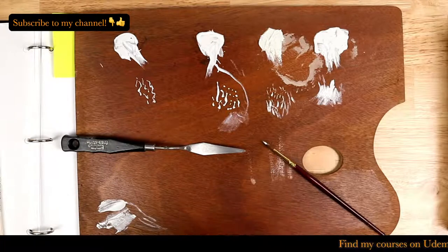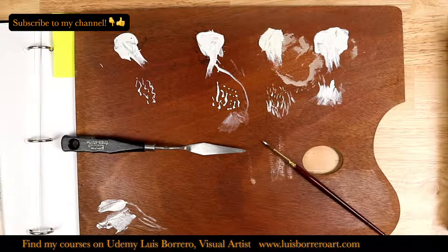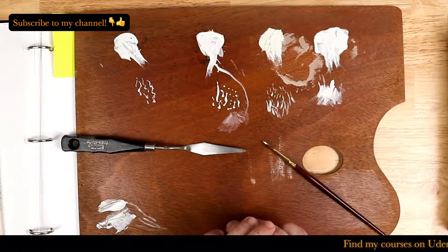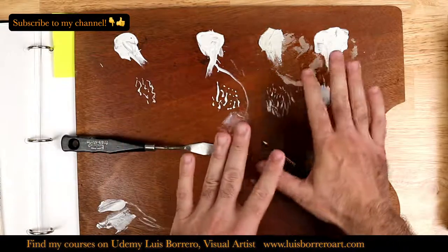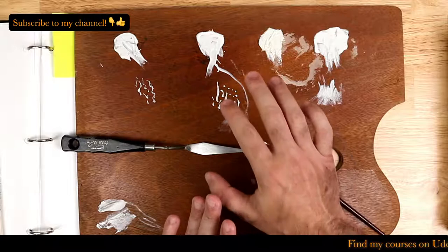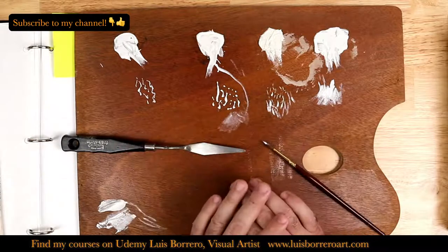Let's see. I have another question from Enzo. Did you have any negative interaction problems with other colors? I have not. I have been making this pigment for 20 years, and I have never had any problems with the lead white interacting or turning black. There's some documentation that says that it turns black. Now, if it's not properly washed, you will have problems. The pigment will not be serviceable. It's going to be a very yellow paint, so it's important to wash it thoroughly.